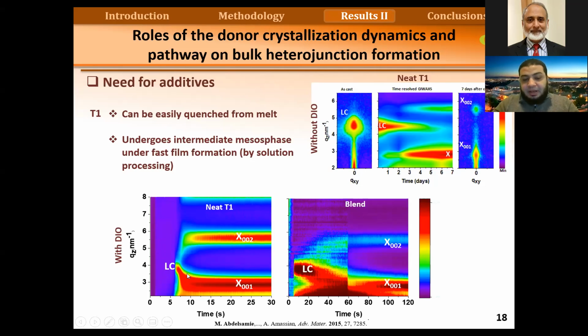So we use some sort of additives that can dissolve the liquid crystalline phase, which we don't want in the final product. We found that the additives can dissolve the liquid crystalline phase and help to form the highly crystalline phase within seconds or tens of seconds if we have blends. So when we blend it with acceptor, it takes a slightly longer time to transform from the liquid crystalline phase into the final phase.